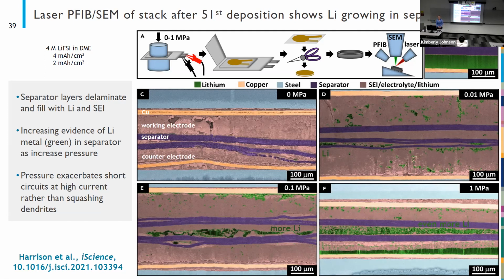There has been some, well, actually, we have also done some work looking at performance at varied temperatures with the 4-molar lithium FSI and DME electrolyte and some of the related, they call them locally high concentrated electrolytes. So I do think that temperature is a super critical parameter because it changes everything about kinetics. It changes the conductivity of your electrolyte. It changes the surface reactivity, sort of the kinetics of electrochemical reactions, right? And so all of that is going to change which overpotential is going to dominate, right? You're always balancing, is it going to be the activation overpotential, the concentration overpotential, the IR drop, the mechanical overpotential, or some other factor in the system.